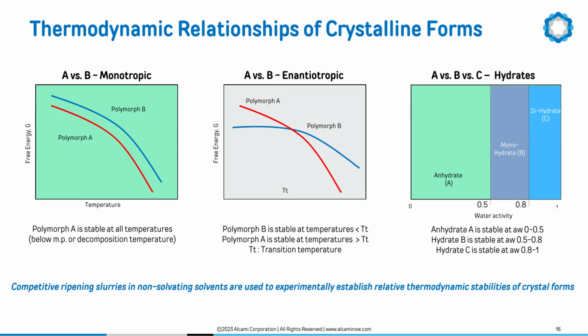An important portion of a detailed polymorphism study is assessment of relative thermodynamic stability of discovered forms. True polymorphs can exist as monotropes and enantiotropes. In a monotropic system, one polymorph is more stable than the other at all temperatures. In an enantiotropic system, one polymorph is more stable below the transition temperature, and the other polymorph is stable above the transition temperature.